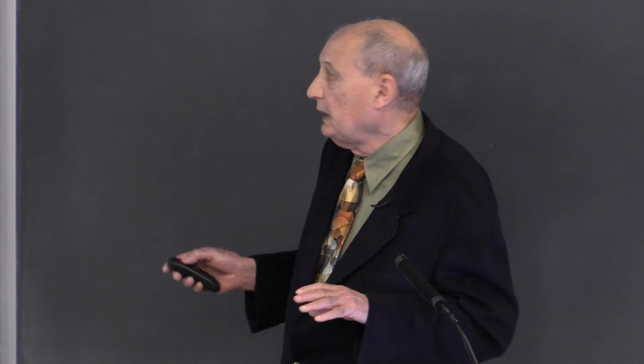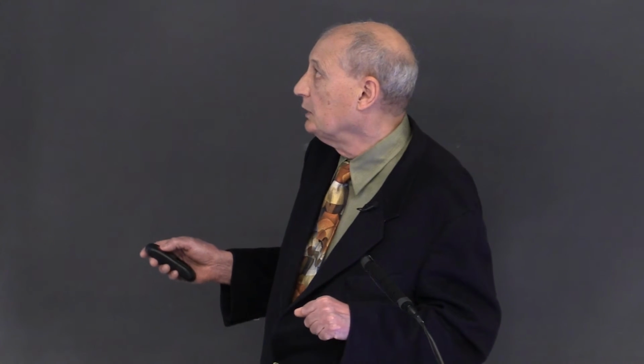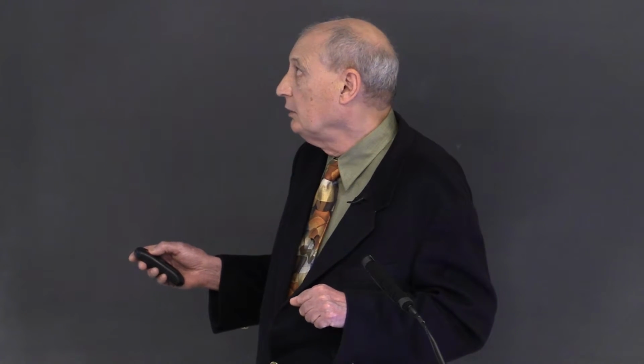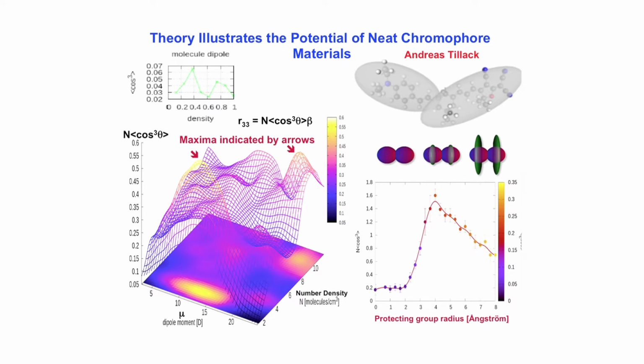Now, if you go to high number density, life becomes much more complicated. First of all, chromophore shape becomes more important because the chromophores are packed in more tightly. So Andreas found that the single ellipsoid was no longer a good representation of the chromophore. And in fact, he had to use two ellipsoids, or a level of detail of 2, to get quantitative simulation.